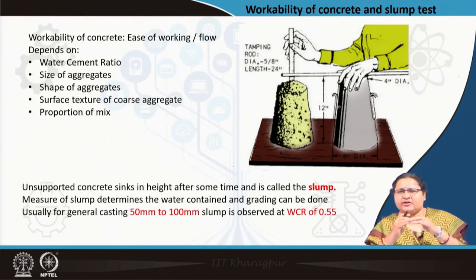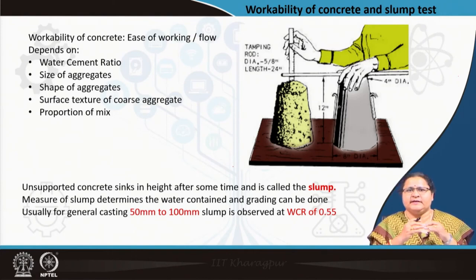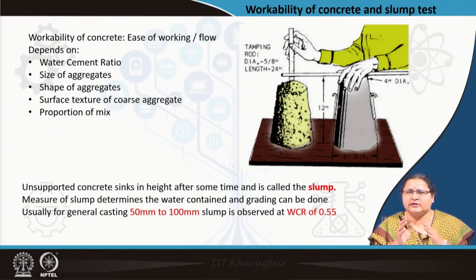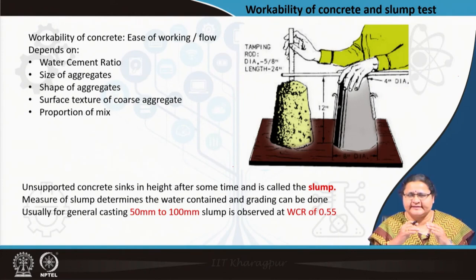This gap is how we measure the slump — the difference between the height of the actual container and how much the concrete has settled. This happens mostly because of the water content in the mix. For general casting, the slump value should be 2 to 4 inches (50 to 100 mm), where the water cement ratio will be within 0.55 — our desired value.